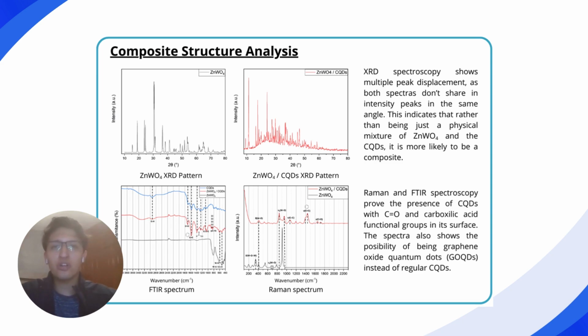Now, about the structure of zinc tungstate, carbon quantum dots, and our composite, we measured an X-ray diffraction pattern, the FTIR spectra, and Raman spectroscopy for the three powders. However, carbon quantum dots measurements, not only for the X-ray diffraction but also for Raman and the gas sensing applications, were faulty due to the high hygroscopicity of the carbon quantum dots. So they are not presented here due to being very faulty and very misleading in the spectra.